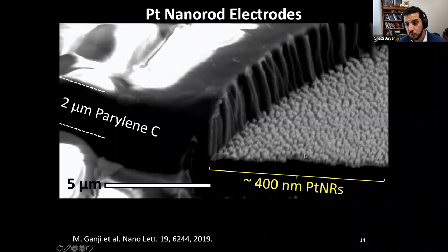These are about 400 nanometers tall, about 50 nanometers in diameter. And they are recessed about 2 microns below the surface of the parylene, so that if the grid is slid on the surface of the brain, they don't encounter shear and break away. So it's important for them to be really recessed at the bottom of the contact.